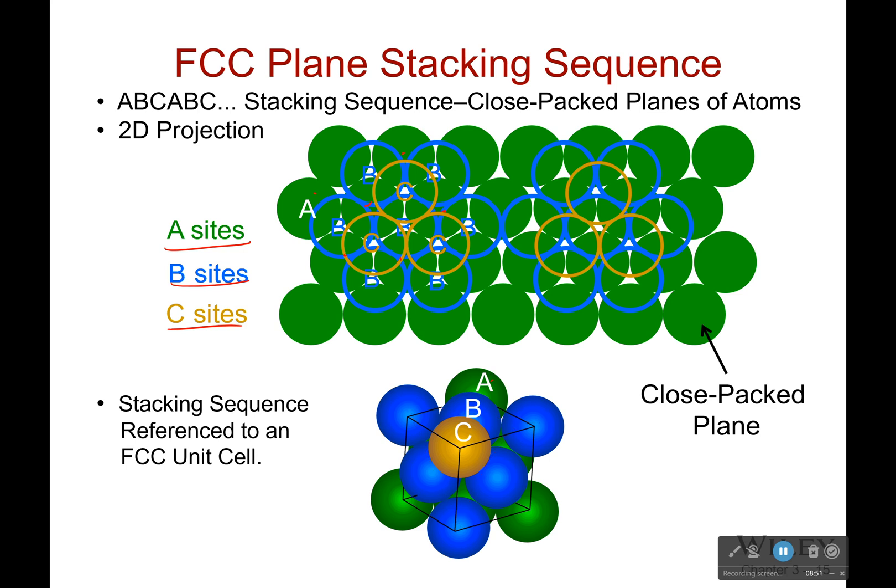If you're wondering why we chose these directions, it's because these are the most closely packed planes. All the atoms touch in these planes. All those guys are touching. Those three are touching. Those threes are touching. And the other planes, the one where if you're going from the top to the bottom. Well, if you look at that one, these two atoms aren't touching. These two atoms aren't touching. So it's not as closely packed. And that's why we don't use that in our stacking sequence.